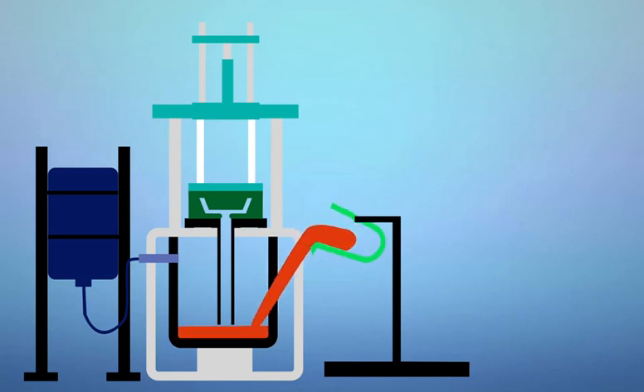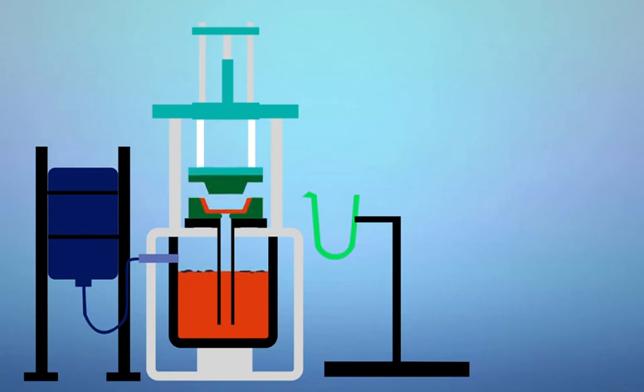The molten metal is then transferred to a holding furnace, crucible, that maintains the temperature and removes any impurities from the metal. The crucible is then pressurized to force the molten metal through a central riser tube and into the die cavity. The low pressure, typically between 10 and 15 psi, ensures that the molten metal flows uniformly and fills the mold cavity without turbulence, resulting in parts with good surface finish, fine details, and few defects.